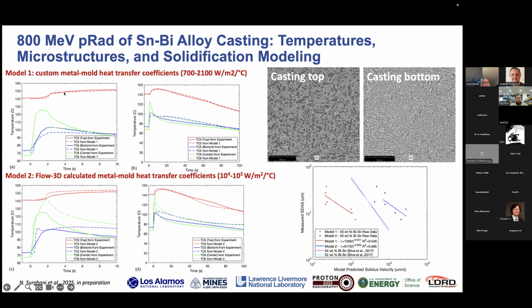So this is an example over here of this zoomed in region of the thermocouple traces as directly compared to the modeling results for these different metal mold heat transfer coefficients. And what was kind of interesting about this is that Model 1 actually did a better job matching, but as I mentioned, Model 2 did a much better job with the fluid flow. So Nadira actually ended up going with Model 2 in this case.